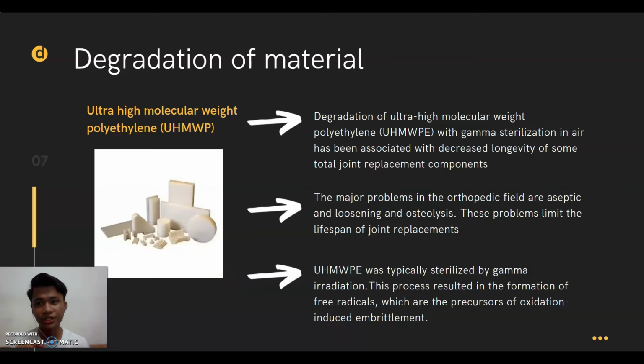Now, we move to the degradation of the materials. So, the first material that we chose is ultra-high molecular weight polyethylene. The degradation of ultra-high molecular weight polyethylene with gamma sterilization in air has been associated with decreased longevity of some total joint replacement components. In the orthopedic field, there are two major problems, which are loosening and osteolysis. These problems limit the lifespan of joint replacement.